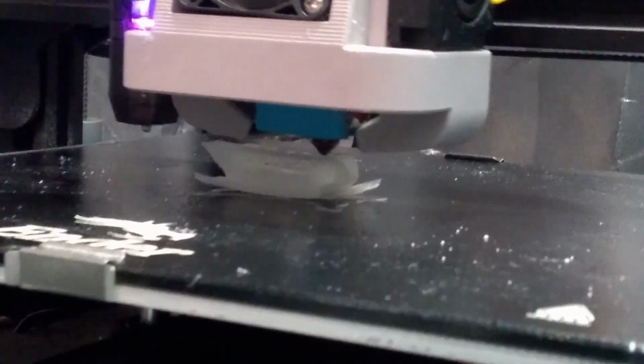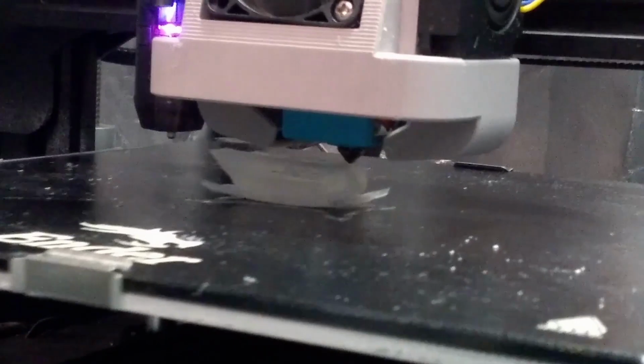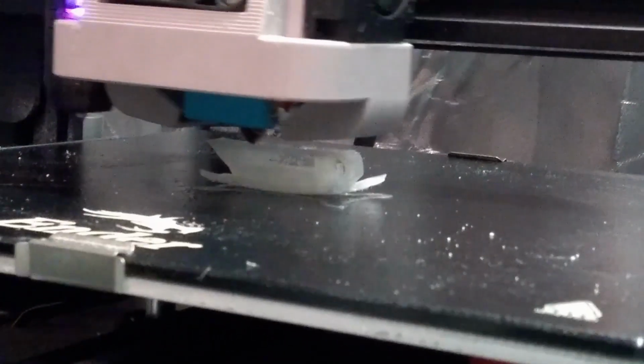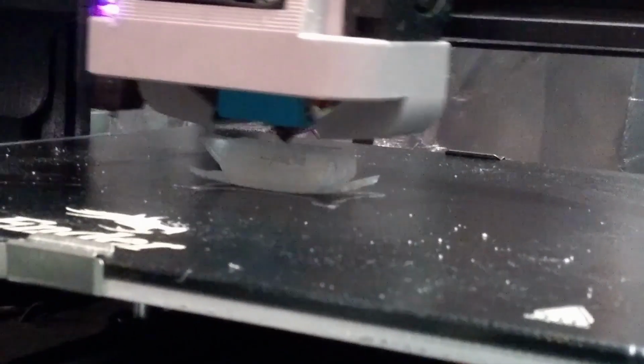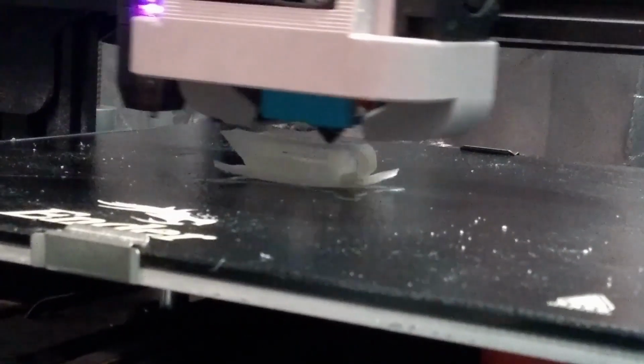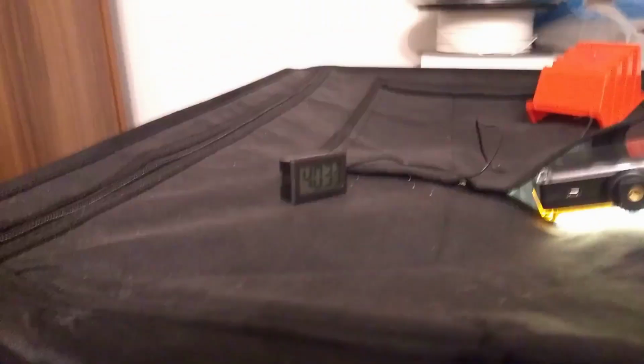Wow, I cannot hear any crack sounds, so the nylon is dry, but look, those corners, they curl up, so the warping is very big. Oh, I will have problems with printing the test specimens. Currently in the enclosure it is 40 degrees Celsius. Probably it needs more.